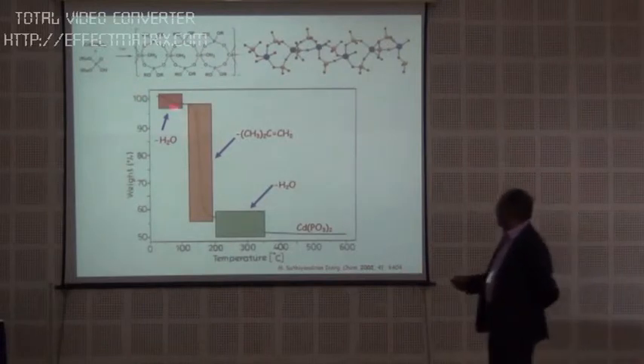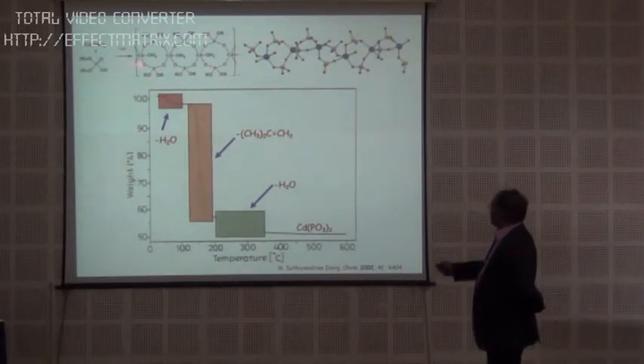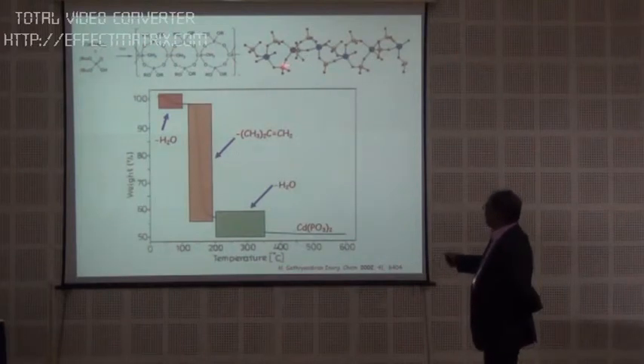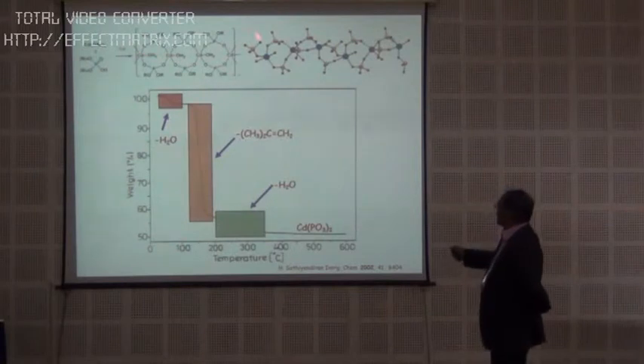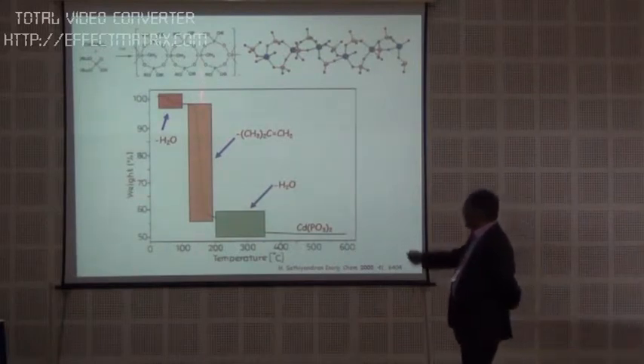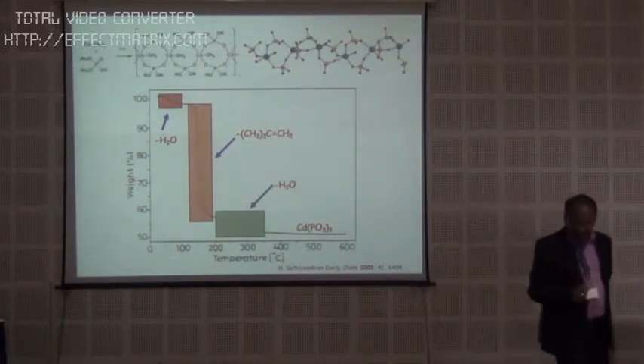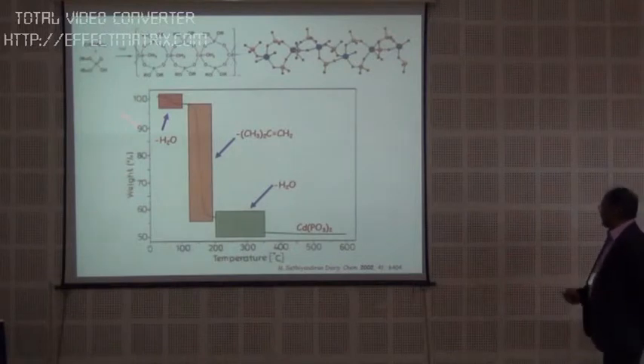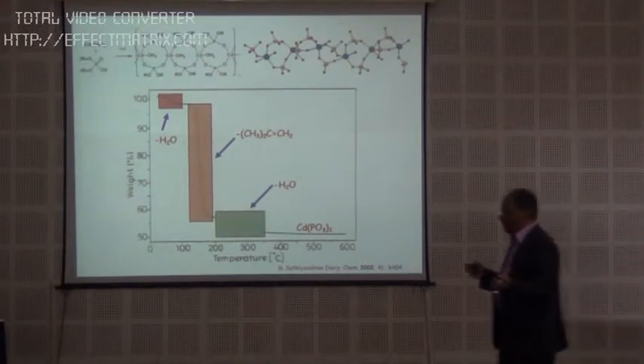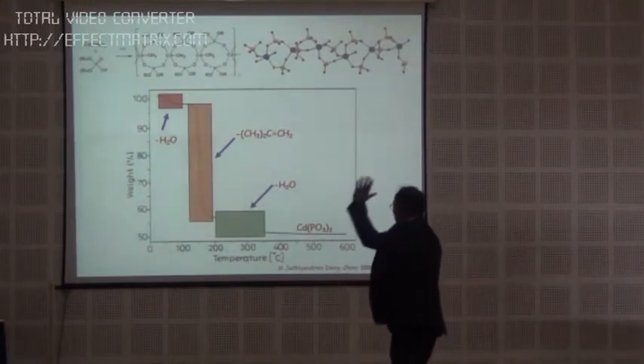Just to show one example, this is a cadmium phosphate polymer made from ditertiary butyl phosphate. This is a one-dimensional polymer. It's pretty much like an iron tube or iron rod coated with paint, something like that. So you have 2 organic groups at the top. Now we can take this and heat it up, and look at the temperature at which the organic group walks off. At 140-150 degrees centigrade, you lose all the organic content as isobutene gas. It's a very nice byproduct because you don't have to work up, it just goes off.